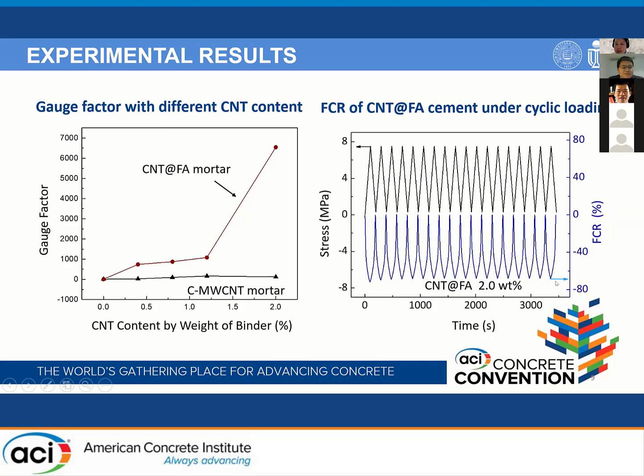and this large resistivity change further confirmed the ultra-sensitive piezoresistive behavior of CNT and FA cement composite. And this phenomenon lasted up to 40 cycles with high signal-to-noise ratio. This phenomenon suggests that this type of cement sensor also exhibits a very stable piezoresistive behavior under cyclic loading.